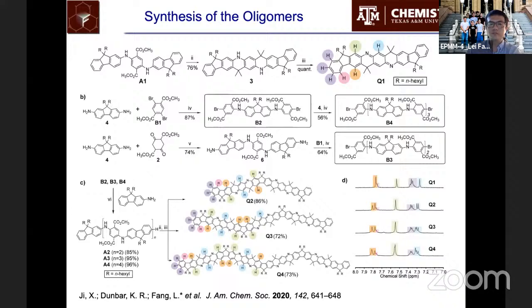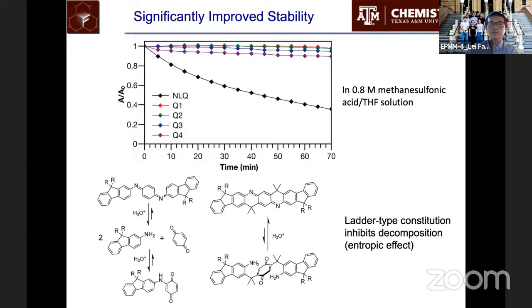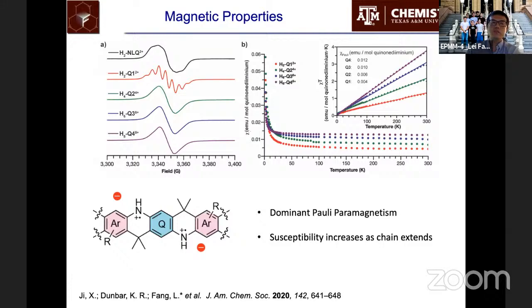So this is the synthesis, which I will not go through. The first important thing is that once these are synthesized, it shows much better stability compared to conventional polyaniline derivatives because of the additional strand bond locking the constitution, so that it's entropically unfavorable to break the bonds. Very interestingly, we now could fully oxidize the compound and fully protonate it. Now we could study the pernigraniline salt without worrying about its decomposition. We could see it has a very strong EPR signal, but more interestingly, it shows very nice Pauli paramagnetism, indicating that there's a metallic polaron or delocalized polaron in the solid state when you fully protonate it.